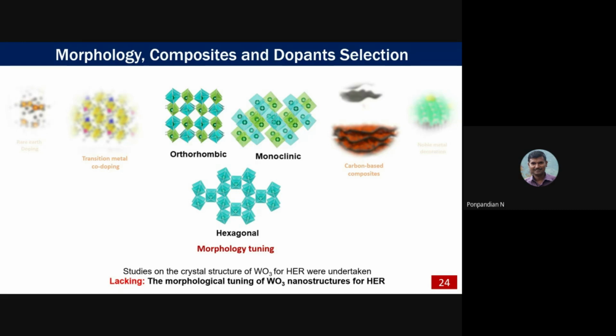The first one is actually the morphological, that is actually the structural dependency. We are making the structure dependent materials. There our choice of material is tungsten oxide. The base material is tungsten oxide. We are tuning the structural properties of the tungsten oxide. First, we are changing the structure from orthorhombic to monoclinic, hexagonal. In that way, we can tune the structure of this particular tungsten oxide. In that way, also, you can improve the efficiency of the catalytic activity. Here, these are studies on the crystal structure of tungsten oxide for hydrogen evolution reaction.